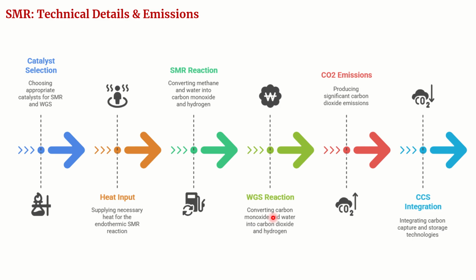So the carbon monoxide produced is further reacted with steam in a second step to produce additional hydrogen and carbon dioxide. This occurs at lower temperatures around 200 to 450 degrees Celsius in the presence of a catalyst like iron, chromium or copper zinc catalyst. And this is the integration. This process integrated with carbon capture and storage can yield blue hydrogen. If the carbon capture and storage is omitted, then it produces grey hydrogen, which is around 9 to 10 kg of carbon dioxide per kg of hydrogen produced. And when it is integrated with carbon capture and storage, the steam methane reforming process can produce blue hydrogen.